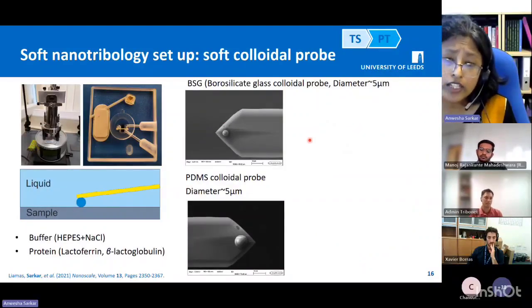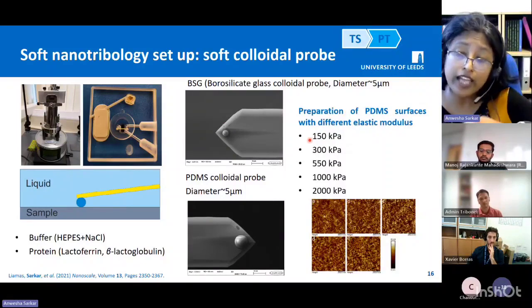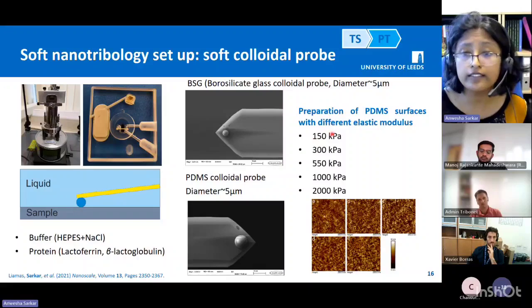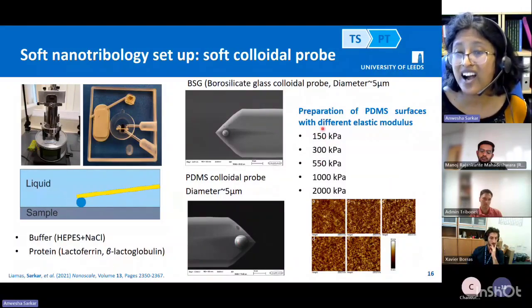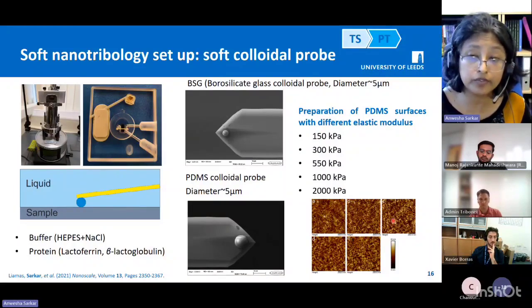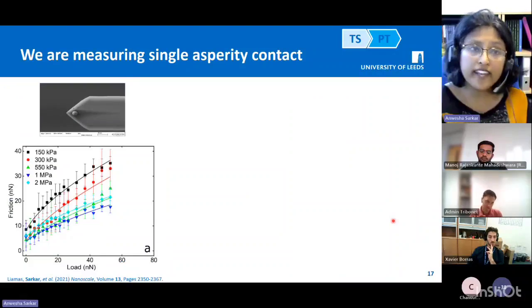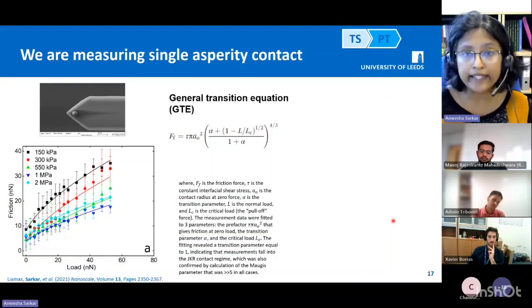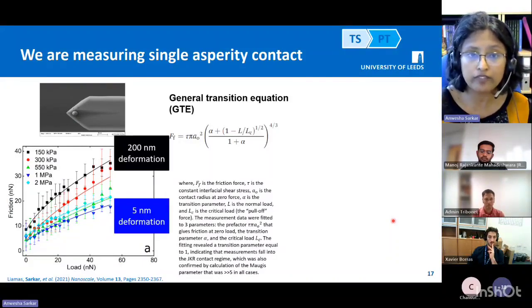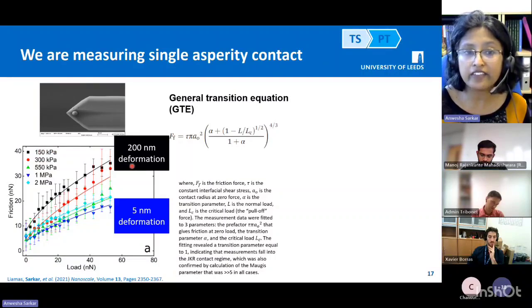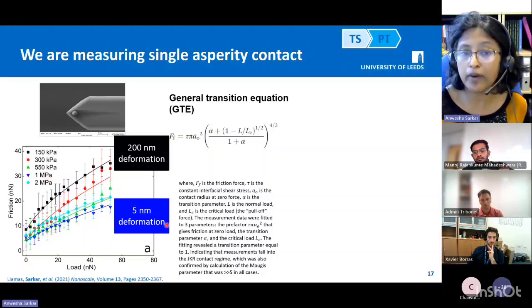So we use the same technology, but here what we did is we actually made PDMS with different kinds of cross-linking and base ratios, and we can make PDMS surfaces and the colloidal probes also at so low stiffness, so 150 kilopascal to 2 megapascal. And they were not different in their roughness, which was pretty exciting. When we did it, what we identified was, of course, depending upon the kind of deformability, you have very different deformation. So for example, if you have a 150 kilopascal probe, it had a very, very large deformation because it was soft. Whereas if you have a 2 megapascal or 1 megapascal probe, you have a much, much smaller deformation.